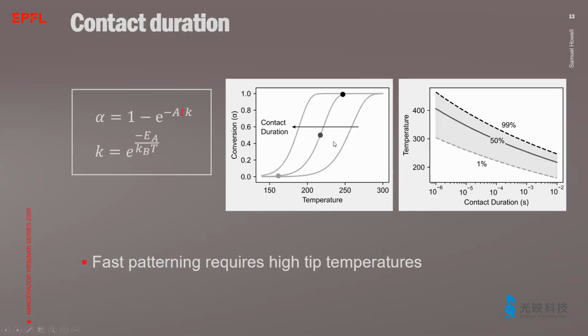The third important parameter is the contact time between the tip and the sample. As can be seen in the graph, for shorter tip sample contact times, the reaction curve shifts towards higher temperatures. The temperature necessary to complete the reaction depends logarithmically on the heating time, or in other words, the faster the writing speed, or the shorter the contact time, the higher the temperature that is necessary to complete the reaction. This is the reason why for TSPL often higher temperatures are necessary to complete the reaction within a few microseconds as compared to the macro scale where much longer heating times are used.